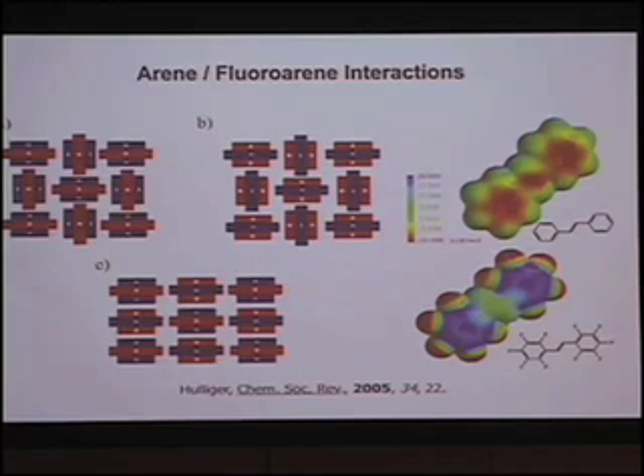If you look at the conjugate molecule, typically diphenylstilbene, because the pi electrons are delocalized along the conjugated backbone, you have electrons centered along the center part of your molecule. So the center part is electronegative, the outside part electropositive. And if you substitute this molecule with a fluorine atom, because of the high electron affinity of the fluorine atom, it sucks electrons to the edge, and you can see a much higher electron density there. So the center becomes electropositive.